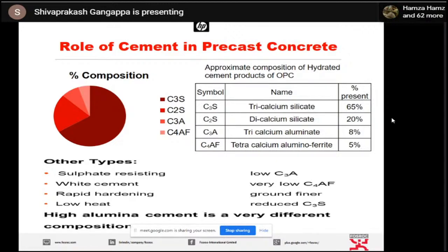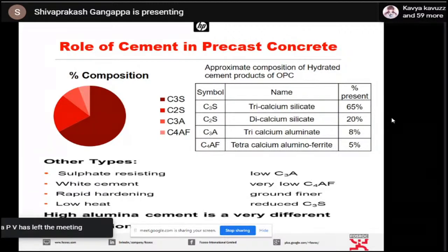In this particular process, what happens? You have to mix it, you have to transport it, and you have to place it. To do these three actions, what we call as workability. Workability is nothing but mixing, transporting, and placing. If you don't get a sufficient amount of time, then what happens? This concrete is useless. It will not be in a position to be used. So you need a retention in between. Once we get concrete retention, then we are supposed to trigger the silicates to a greater extent, aluminate to a smaller extent, so that we could get higher strength, which results in producing a high performance concrete. Now, let's come to the definition of what is high performance concrete.